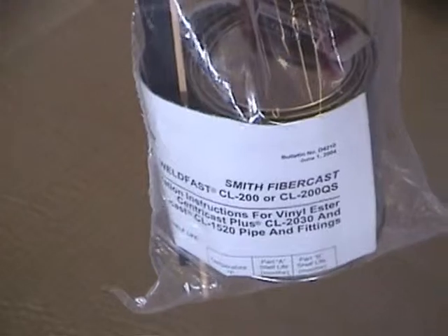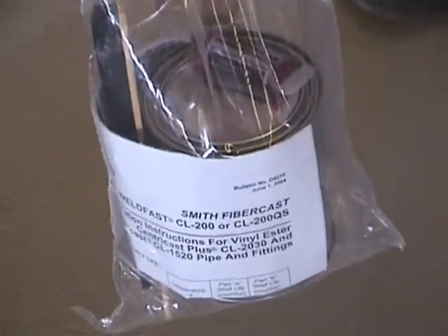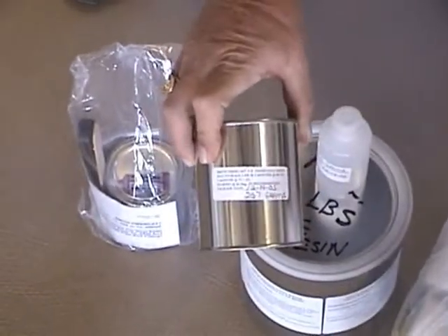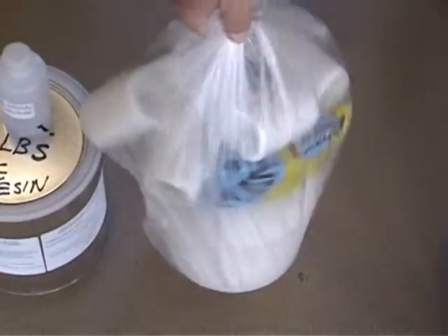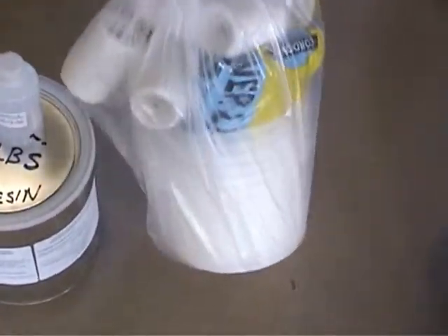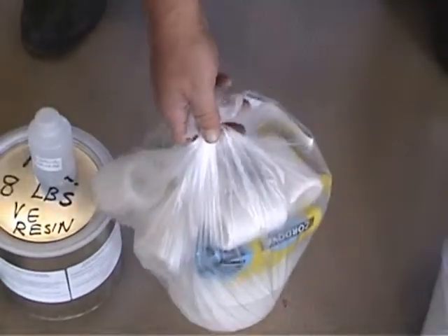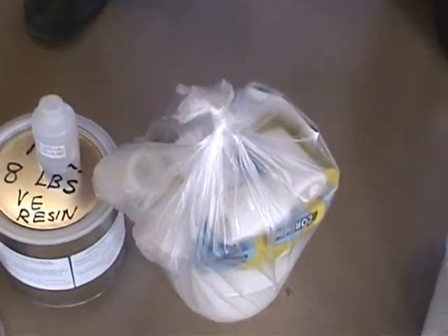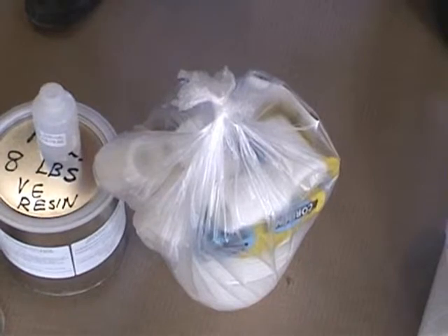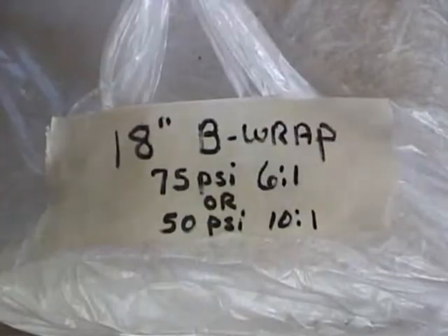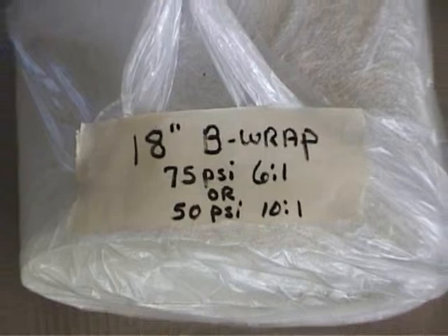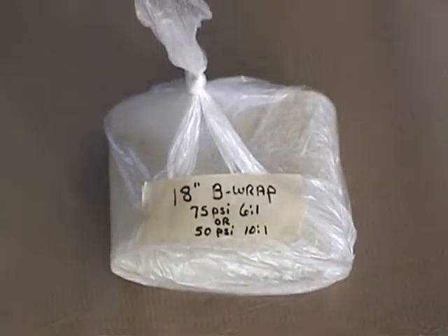Contents include the appropriate adhesive package for the resin system that you're working with. This is used to coat the cut ends of the pipe and bridge the pipe together. Catalyst, resin, finish coat resin. All of your consumables are included, including rollers, mixing buckets, rubber gloves, stir sticks, measuring vial for your catalyst resin ratio, and the cut-to-length butt wraps with glass pre-cut to length.